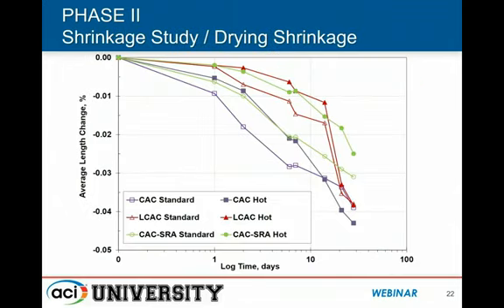And then when we examined shrinkage and overall volume change behavior, we didn't really see a whole lot of improvement. So what was interesting here is we were achieving the durability, as I said, with scaling resistance, but not necessarily the shrinkage resistance that we wanted.